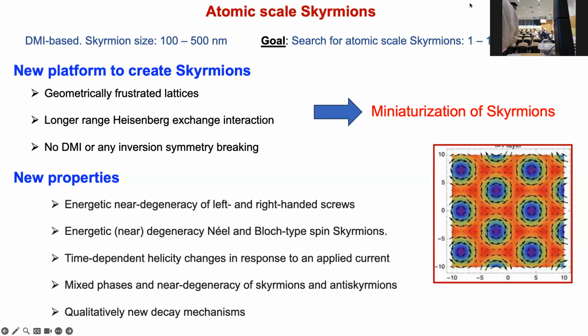These include near degeneracy of left and right-handed screws, which are precursors to the skyrmions, and near degeneracy of Néel and Bloch type skyrmions, which also leads to time-dependent helicity changes. That is, by applying a small external field, you can change the helicity of the skyrmions. There arise mixed phases and near degeneracy of skyrmions and anti-skyrmions.